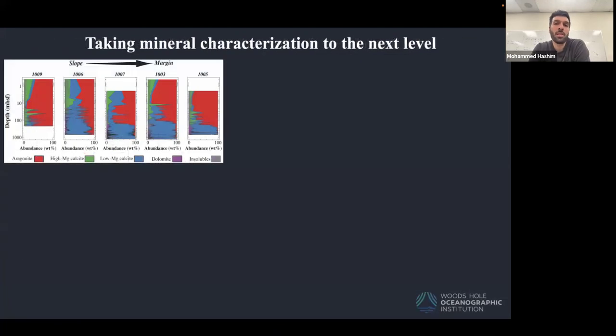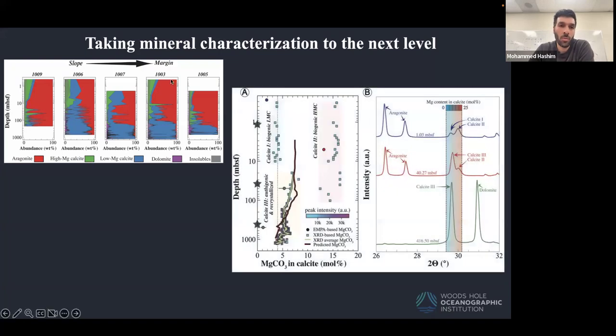But the other thing we decided to do was to do high resolution mineralogical characterization using X-ray diffraction. And again, ODP legs do that on the ship, but generally they do this very quickly on a lot of samples without standards, without calibration. So it is useful. The data they produce is useful, but it's limited. So we decided to take samples from one of these sites, 1003, and collect high resolution mineralogical data. And we were able to observe really interesting patterns.